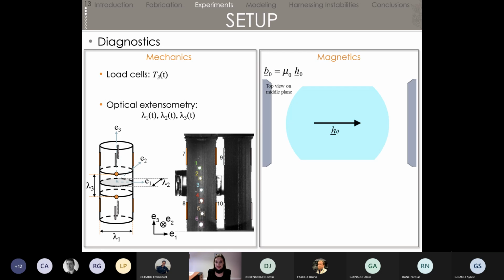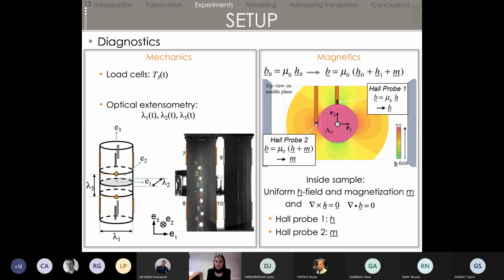Now, for magnetics, it's a little more complicated. So when you have a uniform magnetic field here in air, and then you put a sample in it, what happens equation-wise is that you have M, which is the magnetization of your sample, and then H1, the perturbation field around your sample. So in practice, when we put our sample, we see that. The pink circle is the sample. Because its cross-section is circular, we have uniform magnetization inside that sample, but we can see all around that the field is perturbed and is no longer uniform.